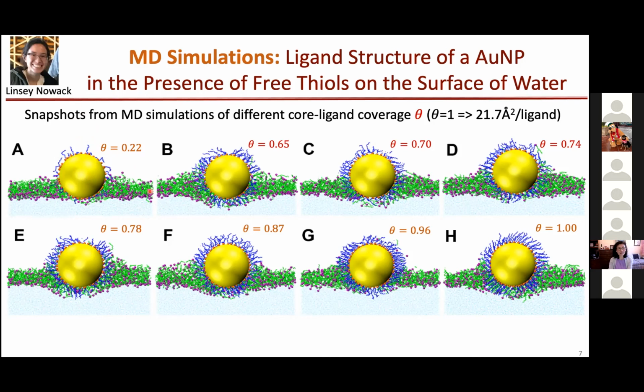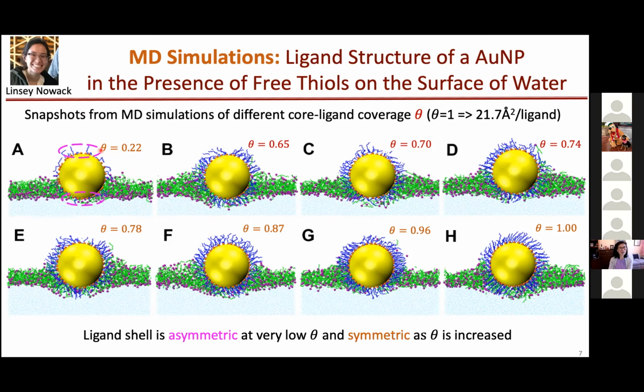At very low gold core ligand coverage, the thiol distribution at the bottom of the spheres and top of spheres is asymmetric, thinner at the bottom than the top. But as you move to higher thiol concentration, the ligand distribution becomes more symmetric.